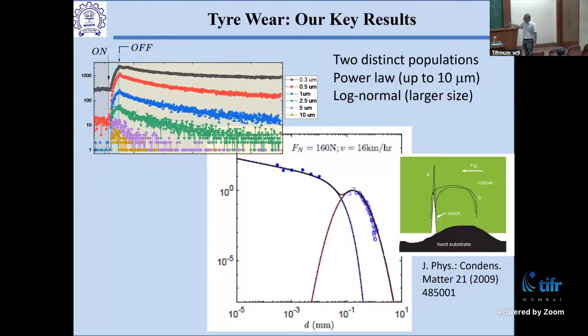And then when we stop, in principle, there's no place to go, so they shouldn't decay. But there are some quirks in why this happens, that there's a small decay. But notice that the 10 micron particles come off, we stop the tire, it all falls down, and there's no more 10 micron plastics you can measure. The 300 nanometer plastics are going to stay in the air for a really, really long time. This is actually a couple of hours.